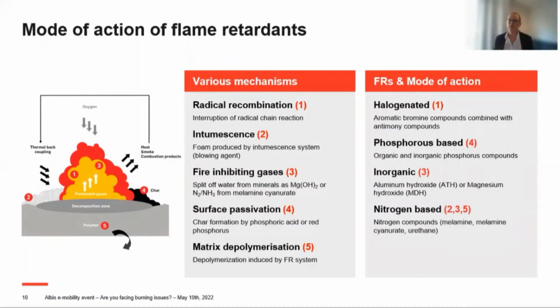And this can be done by different kinds of flame retardants. Like I said, we do have halogenated flame retardants, but we also do have halogen-free flame retardant systems, like the phosphorus-based ones, the inorganic-based ones, or the nitrogen-based ones. And typically, you often don't have only one flame retardant system, but you often have a combination of different flame retardant systems, for example, with some kind of synergist. And by this, you then also have different mechanisms working depending on which flame retardant you choose.